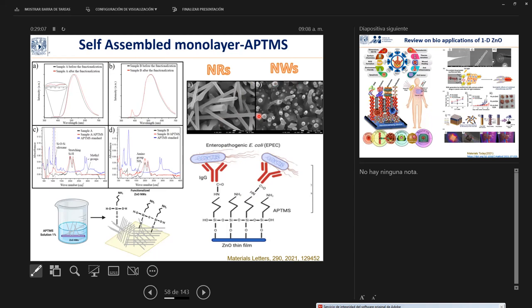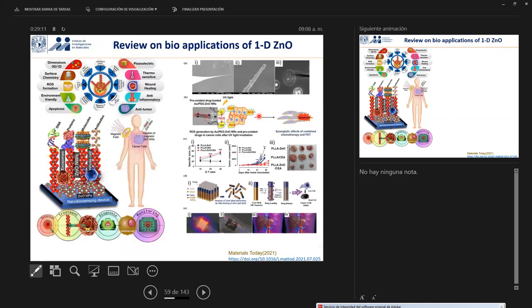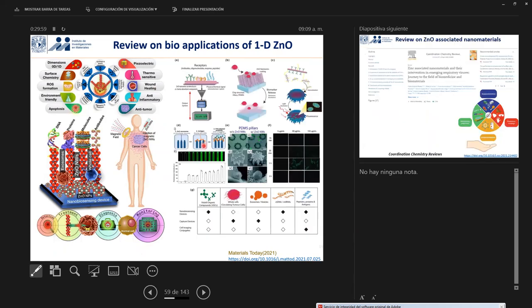And I think in some months, in a year or two, we can show you the advances in that particular part also. Apart from that, recently we have also done some review studies, state of the art of zinc oxide materials for cancer detection and treatment. In this part, we have found that there are some reports, a limited number of reports, on the detection, treatment, diagnosis, and monitoring of cancer cells, for example. And we have found that nanowires, in this case especially, produce reactive oxygen species, which can finally lead to apoptosis of cancerous cells. This is one of the main ideas we are exploring now. We haven't started any experimental work on this, but we have found that zinc oxide nanowires have very nice potential from the detection to the treatment of cancerous cells. And in diagnosis also, people are using these nanowires because they have green emission. So they are using these nanowires and nanorods for the detection of cancerous cells.